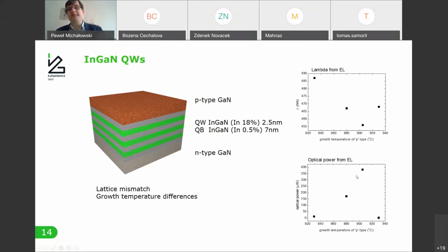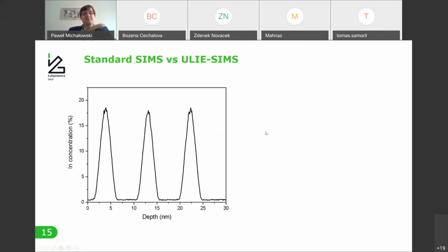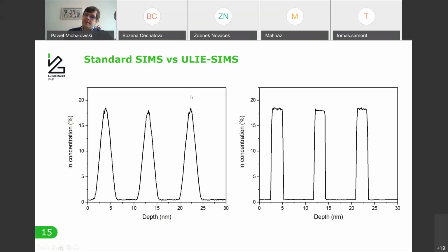So we want to study it with SIMS, but once again, there is a little problem because the typical standard SIMS depth profile produces such an image, but this is not very good because there are just a few data points. You can see a Gaussian-shaped feature, but then I used this ultra low impact energy SIMS. So I reduced the energy, increased the incident angle, and made a procedure that can make such a depth profile much better, which is presented here. Now you can see that these quantum wells are not registered as Gaussian-shaped peaks, but really box-like structures, which is what it's supposed to be. So with an extreme depth resolution in here.